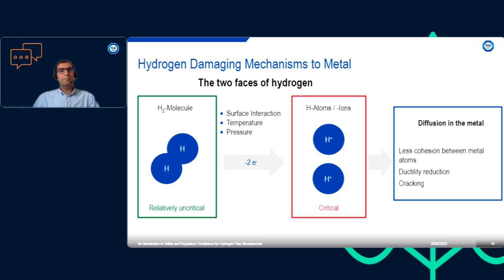So let's look at the mechanisms of hydrogen embrittlement. Hydrogen has two different phases. It has a molecular phase and it has an atomic or ionic phase. When hydrogen is in the form of molecules, it's basically uncritical. It doesn't do that much damage to any system. But when these molecules come in contact with the surface or the boundaries of the system, because of those interactions with the surface, the molecules can split into two ions. And these ions, because they are very small, can easily diffuse into the structure of the material.